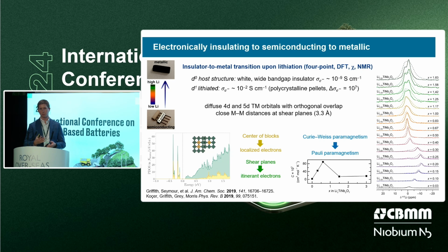concentrations of inserted lithium, so basically by using it as a battery, you're able to increase the electronic conductivity by a minimum of like 7 orders of magnitude. And this is certainly underestimated based on how these measurements are done. So you get something on the order of a 10 million improvement in electronic conductivity just by using it as a battery. It's a kind of self-doping process where you're n-doping this semiconductor to the point that it becomes metallic.